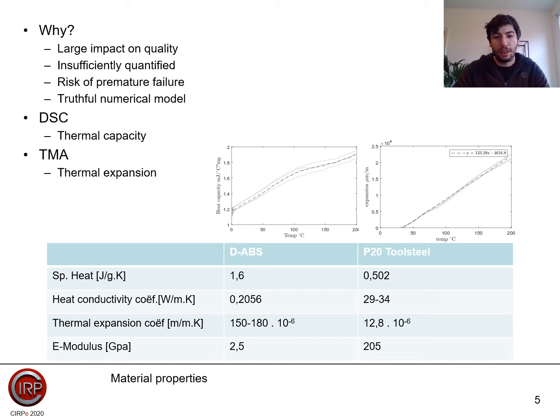Differential scanning calorimetry (DSC) analysis is used to assess the thermal capacity and an interval for the heat deflection temperature within the range of 0 to 200 degrees Celsius. Thermo-mechanical analysis (TMA) is used to determine the thermal expansion. More info regarding these tests is written in the paper.